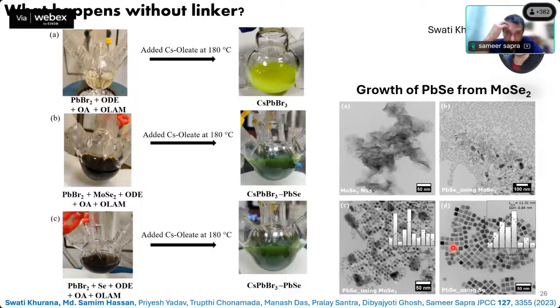and the molybdenum selenide. So, this is your molybdenum selenide nanosheets. And the moment he would put some cesium oleate, it started to break like this. You see these molybdenum selenide sheets start to break like this. And what it does is to form lead selenide nanocrystals. Okay.